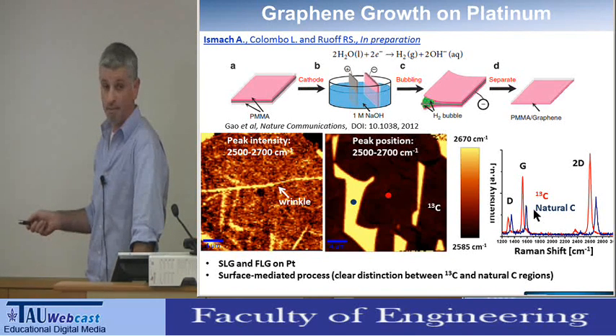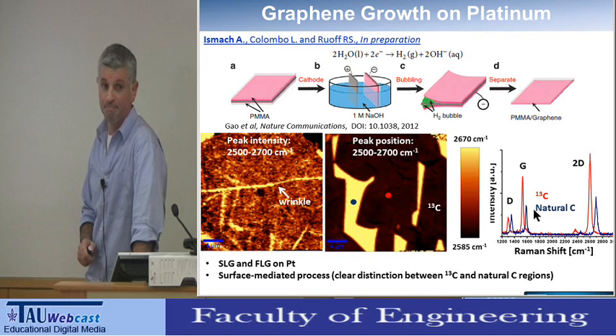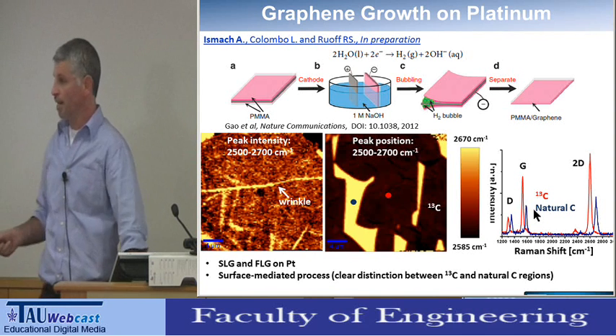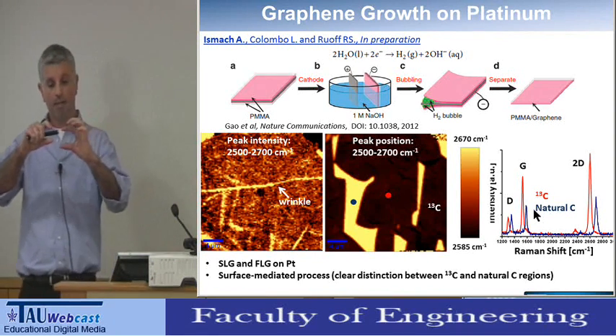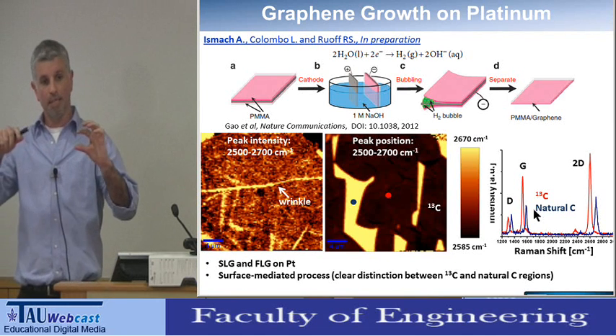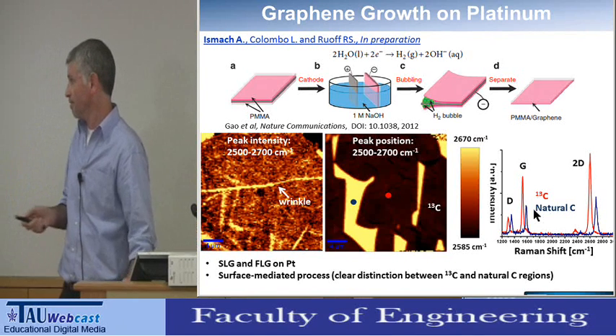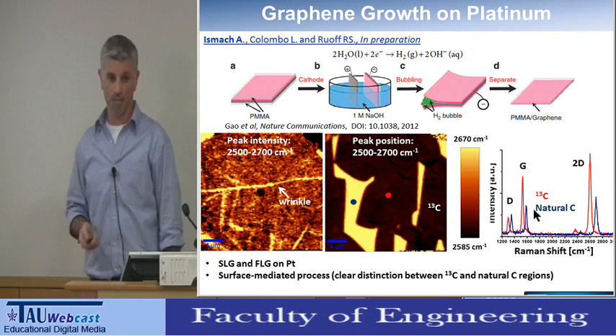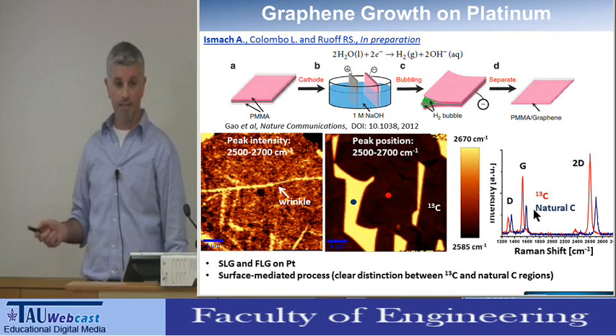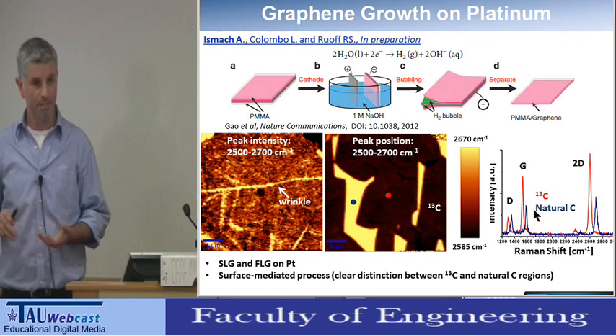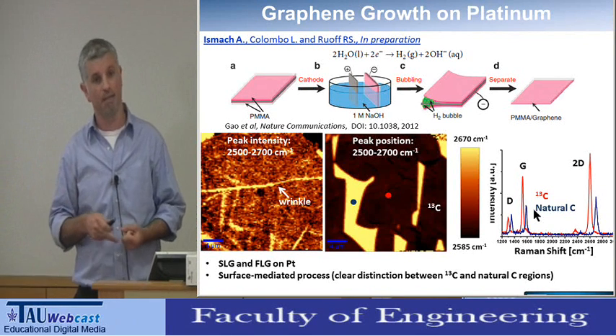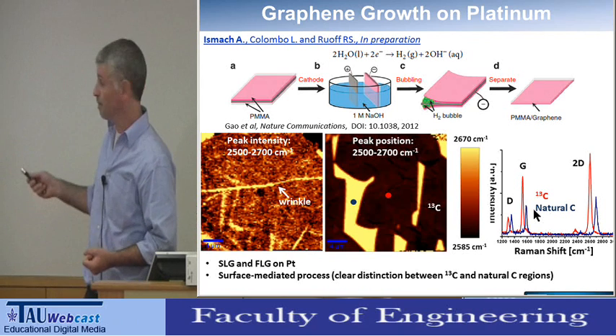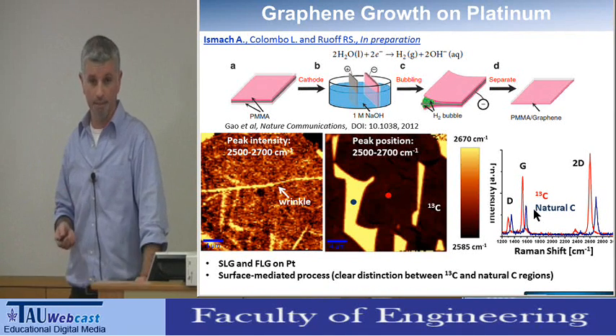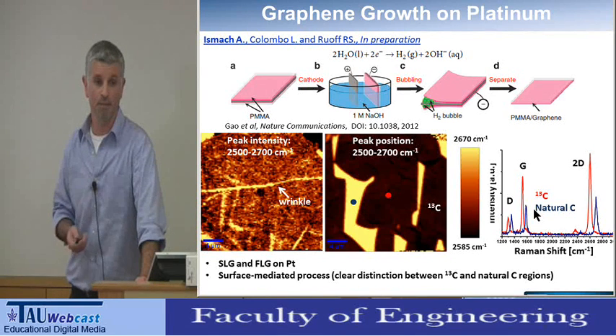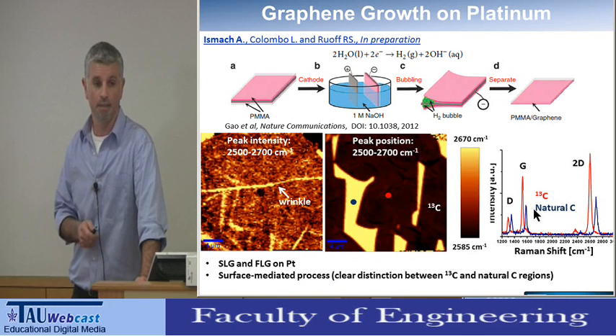Even when I see few layers, I can see the different regions. No, I guess because even when I have few layers, the diffusion is only just below the surface, and it doesn't reach the bulk. My explanation for that, and I'm still working on that, is that in the platinum case, the carbon diffusion on the surface of the platinum is much higher than the diffusion into the bulk, and that's why you can get single layer or only few layers, but you can't get in this regime thick layers as you are supposed to according to the solubility parameter.